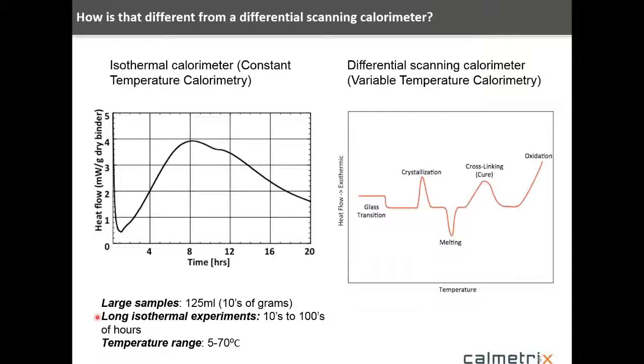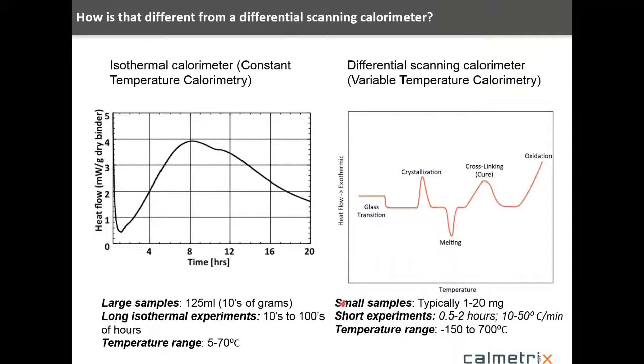The experiments are very long term. They're long isothermal experiments in the order of tens to hundreds of hours. Again, because the things that we're looking at here happen over long periods of time. They're not short-term events. So we need long isothermal experiments, and the instrument is designed for that. And then we're also usually interested in a fairly limited temperature range with these applications, say from 5 to 70 degrees C.